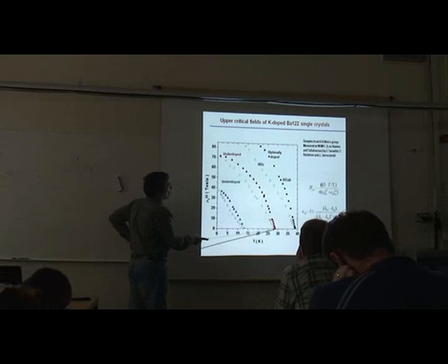But later, people have done a lot of studies on these materials, and again, they all show similar behavior. The slope here can be very high. So if we calculate the coherence length from the slope, assuming Ginzburg-Landau theory, you get a coherence length of maybe a fraction of a nanometer, only a few angstrom.